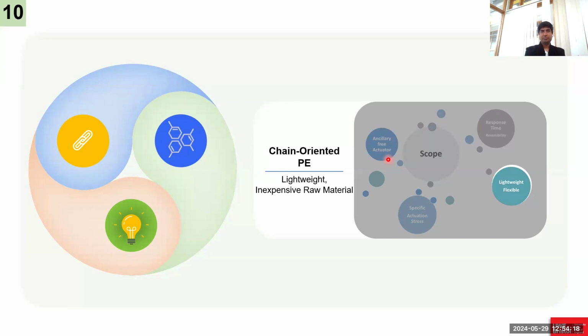Polyethylene is an interesting material because at the molecular level, this material can be attenuated in terms of chain orientation direction. If we draw these materials, we can have a very stiff material with very good mechanical properties like Young's modulus. And also the most important property that we are going to use is the negative coefficient of thermal expansion. So when we orient polyethylene, the chains are oriented, the crystallinity of the material is increasing, and the material is experiencing a negative coefficient of thermal expansion. That means if the material is being heated, rather than expanding, these materials will contract. That will be very helpful.